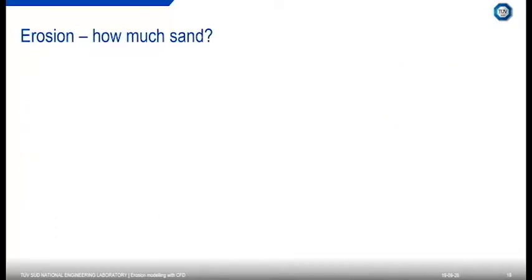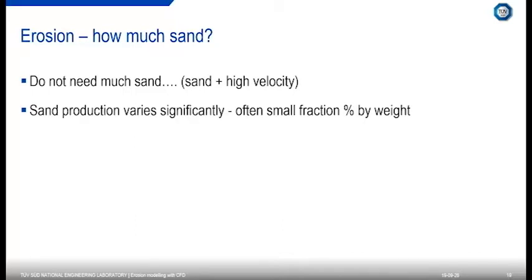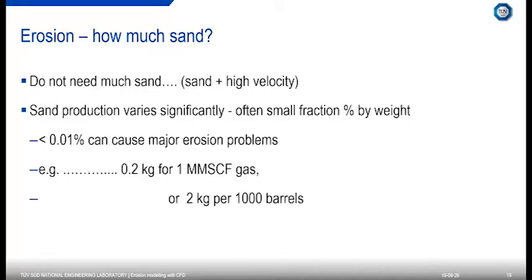So I suppose a good question is how much sand do we need? We don't actually need that much sand. If we have quite a high velocity gas and a little bit of sand, that can cause significant issues. The sand production varies significantly, and it's often only a small fraction percentage by weight. So less than 0.01% can cause major erosion problems. So for example, in that context, 0.2 kilograms per million standard cubic feet of gas, or 2 kilograms per 1,000 barrels. So generally sand content's in the range between 1 to 50 parts per million by weight, but can cause significant issues even at that.